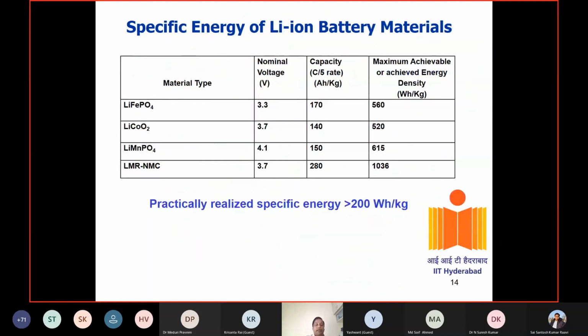Okay, in a similar way, if you calculate, already I told you lithium. If you calculate lithium iron phosphate, which is a cathode for the lithium ion cell, you see it has an energy of 560 watt hour per kilogram. Lithium cobalt oxide 520. Lithium manganese phosphate, you get 615 watt hour per kilogram. There is a lithium manganese rich NMC at 1036 watt hour per kilogram.